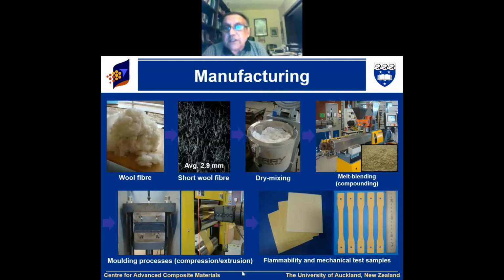So we can extrude a section, or we can extrude a sheet of material 100 meters long, but about half a meter wide. So these processes are possible, and then you can use that sheet material or pre-preg that you have manufactured into molding process, and then from compression and extrusion, we can check the properties, not flammability, but any other mechanical test samples to check the property. So essentially, these are the steps. Take the fibers, mix them, dry mixing, melt blending, compounding, then molding process, and then you can use this sheet material for thermoforming for products as well.